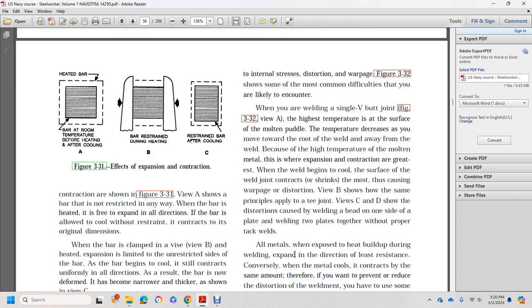When you're welding a single V butt joint, the highest temperature is at the surface of the molten weld, and the temperature decreases as you move toward the root of the weld and away from the weld. Because of the high temperature of the molten weld, the expansion and contraction are greatest there. As the weld begins to cool, the surface of the joint contracts and shrinks the most, causing warpage distortion. View B shows how the same principle applies to the T-joint.